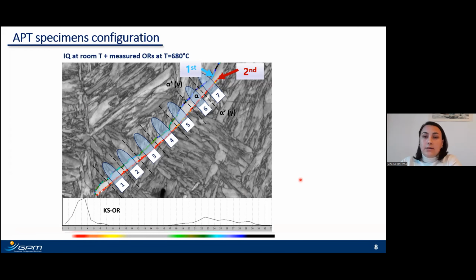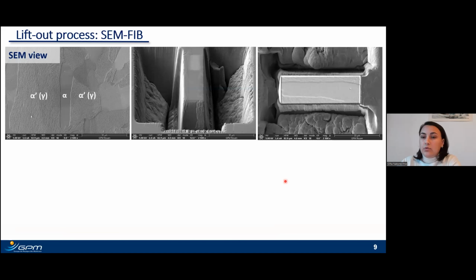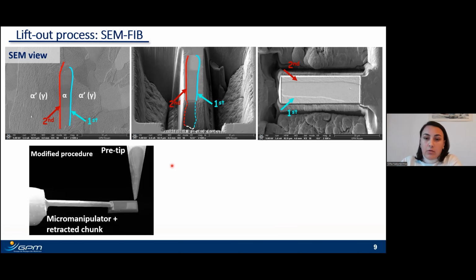To obtain such a set of APT tips, we use the well-known lift-out procedure. During this procedure, we try to verify the interface propagation down into the material, to have it as perpendicular as possible to the APT analysis direction. Then, to provide the desired configuration of the APT sample, as I presented on the previous slide, we were mounting the piece from the extracted chunk on the tip, on the side, as you can see here on the slide.